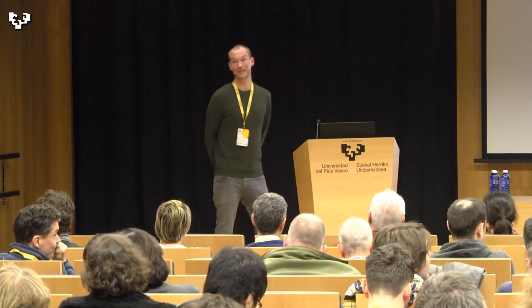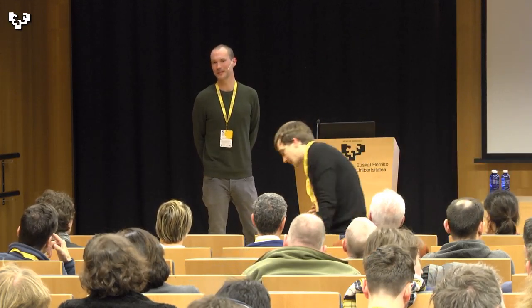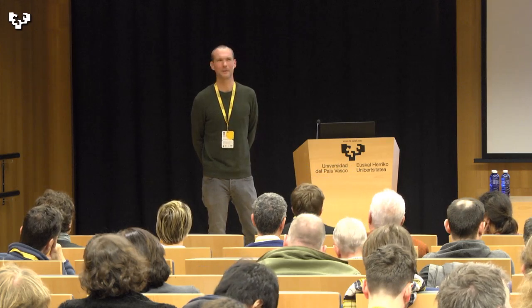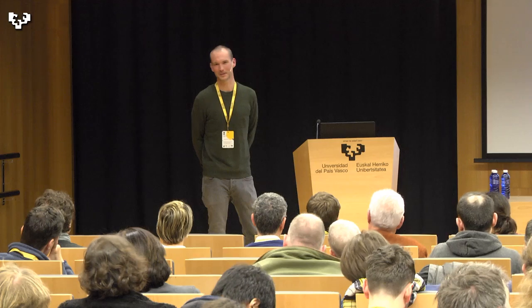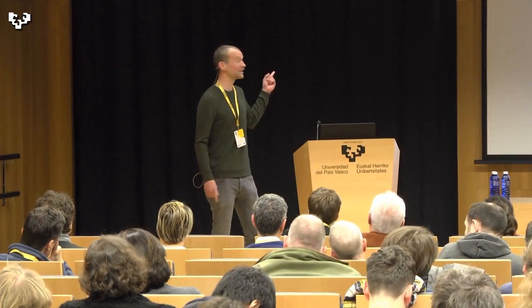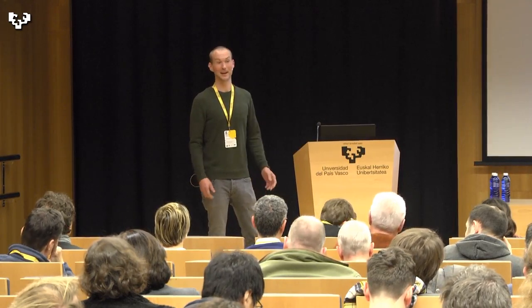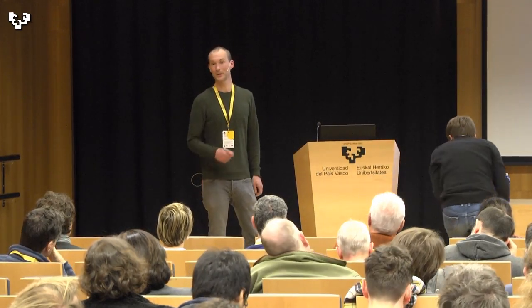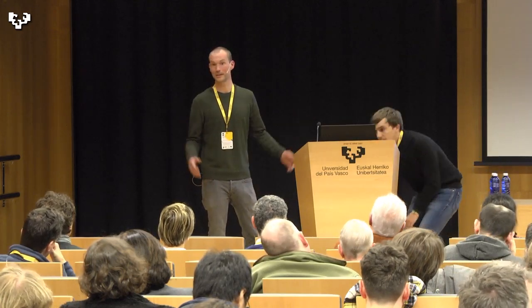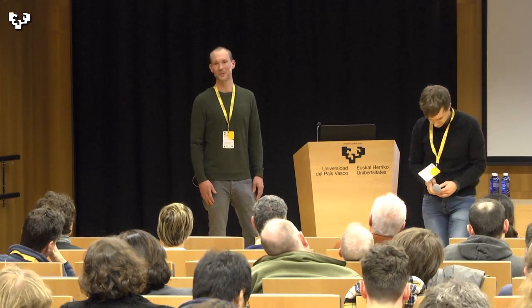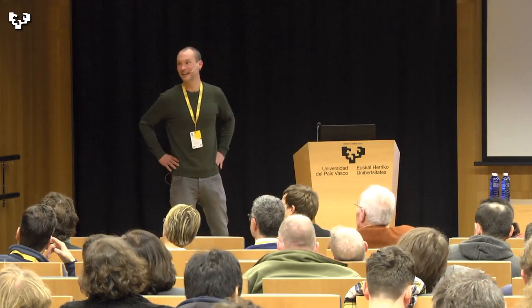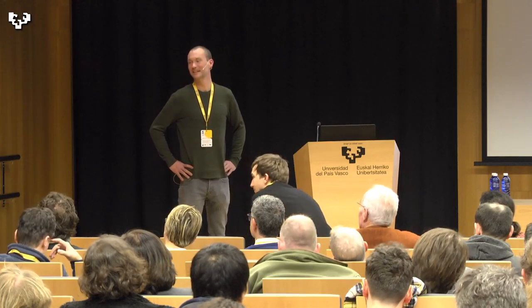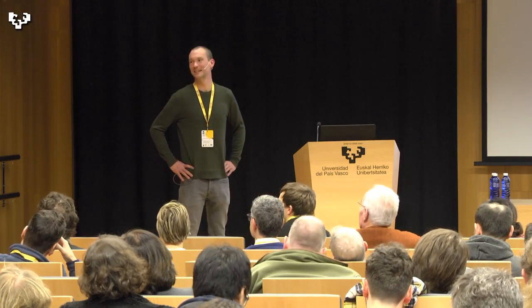I think there are examples where you see that different functionals give different predictions of the topology. But I think mostly that different functionals will predict the same topology, though I'm not so sure about it. We tried, for example, this material I showed you, iron bromide, which we predict to be a Chern insulator. If we add a U to the iron D states, a U of 1 eV, then it's a trivial insulator. I think I have a counterexample of TlNi that is a topological insulator in DFT and trivial in GW.